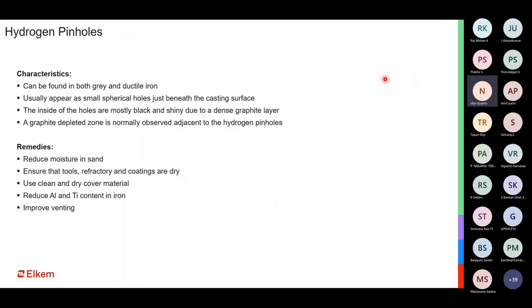When you look at that particular pinhole under a microscope, you would see a very blackish and shiny structure inside the hole, which is because of the deposition of graphite on that layer. The other important indicator is that when you look at the micrograph after polishing, around this particular pinhole we can see regions which are completely devoid of graphite. You would not see any graphite flake just adjacent to the pinhole area. So that is one of the indicators of hydrogen pinhole.